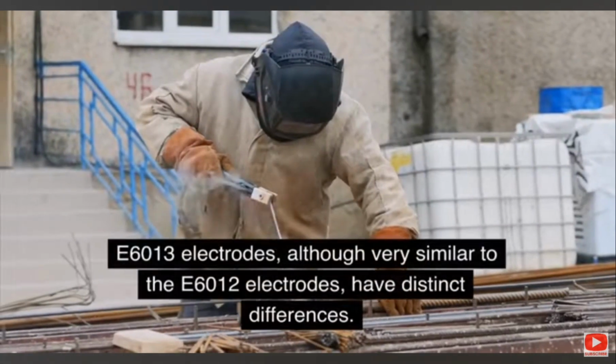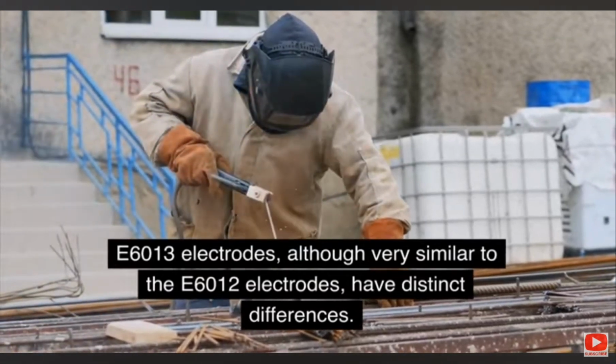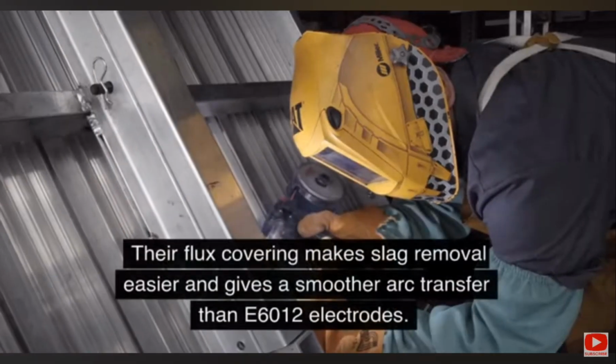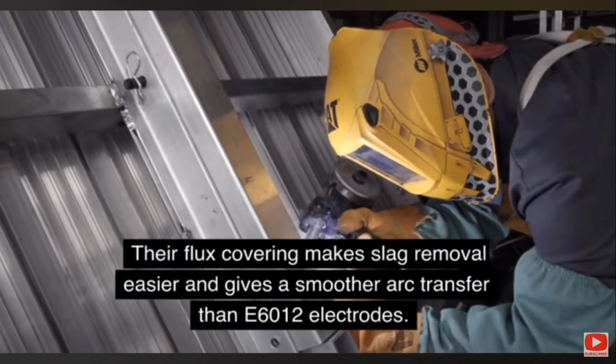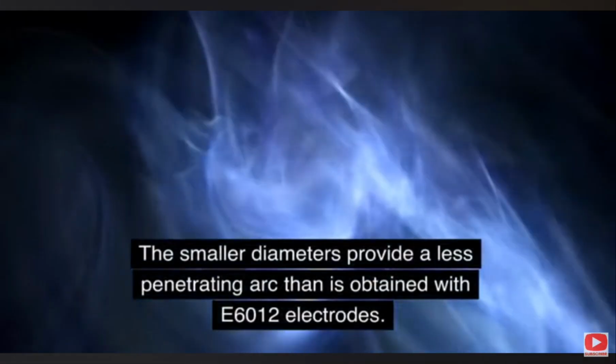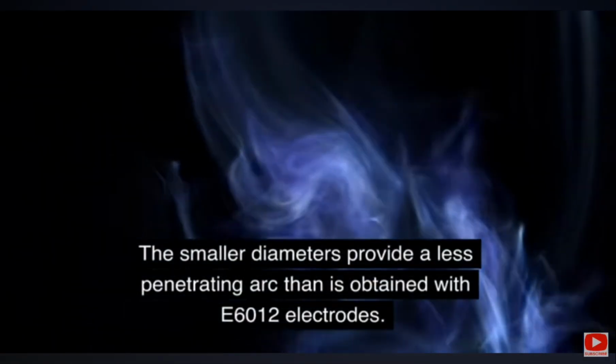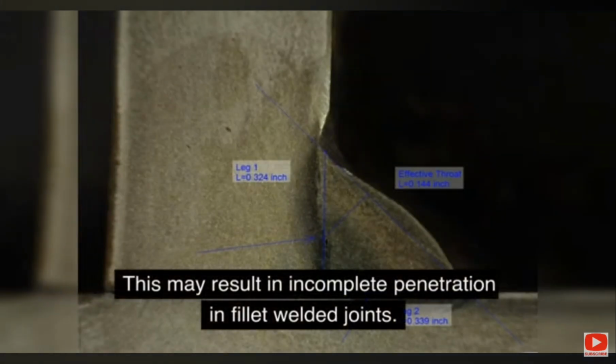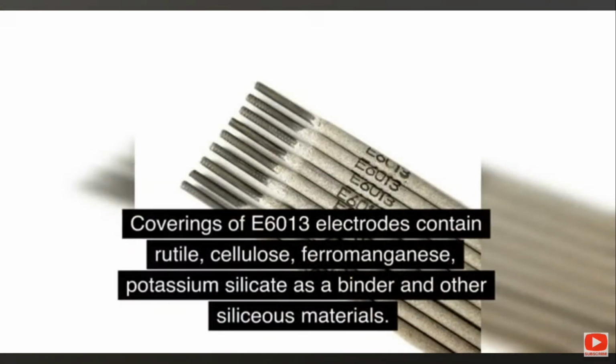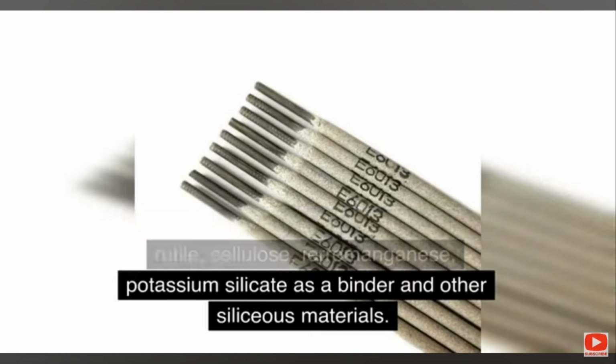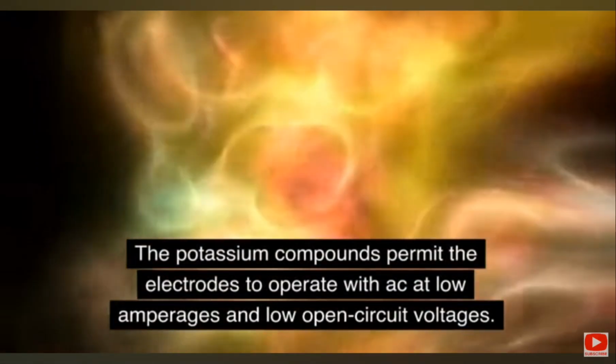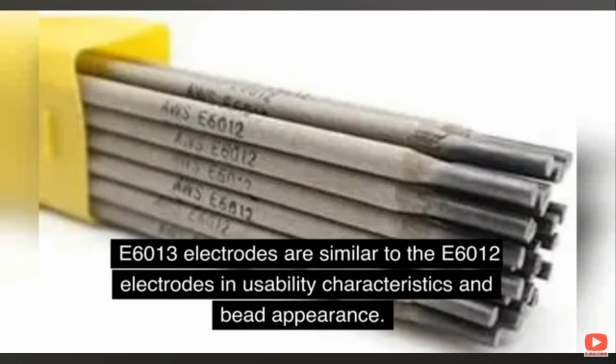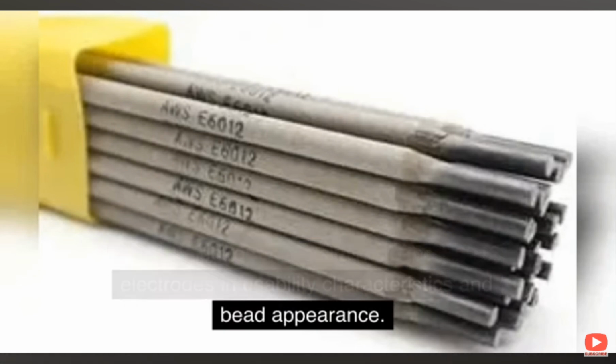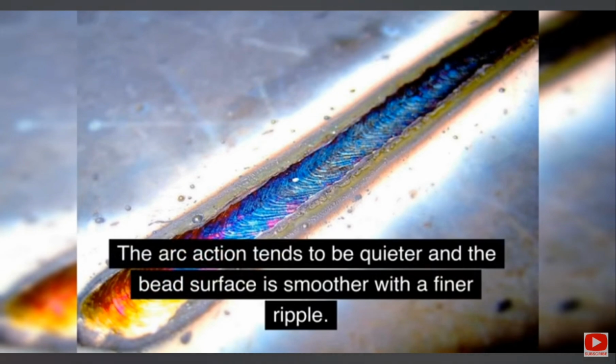E6013 welding rod. E6013 electrodes, although very similar to the E6012 electrodes, have distinct differences. Their flux covering makes slag removal easier and gives a smoother arc transfer than E6012 electrodes. The smaller diameters provide a less penetrating arc than is obtained with E6012 electrodes. This may result in incomplete penetration in fillet welded joints. Coverings of E6013 electrodes contain rutile, cellulose, ferromanganese, potassium silicate as a binder and other siliceous material. The potassium compounds permit the electrodes to operate with AC at low amperages and low open circuit voltages. E6013 electrodes are similar to the E6012 electrodes in usability characteristics and bead appearance. The arc action tends to be quieter and the bead surface is smoother with a finer ripple.